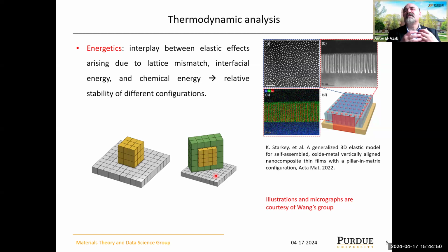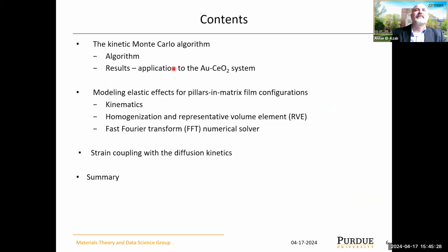It's augmented with the so-called thermal mismatch, because when you cool these things from higher temperature, that contributes to the mismatch in a different way. And that leads to elasticity. So these systems store a lot of elastic energy. Together with the interfaces, there is interfacial energy. And because of composition, they store chemical energy that can be varied or tailored by the fact that the atomic species are mobile or have the freedom to go from one phase into the other. That is the energetic business.